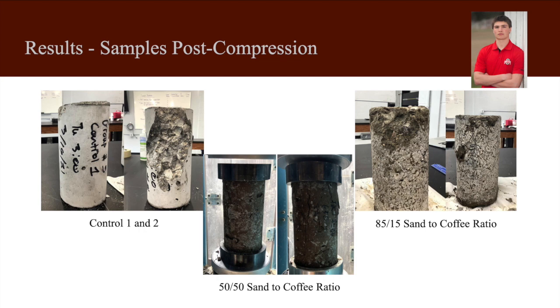Here are the cylinders post-compression tests. The biggest thing that was observed was how the control sample failed compared to how the samples with the coffee grounds failed. The control sample looked as if it broke off in chunks, as you can see on the left side, and the time span of the failing was almost an instant. For the coffee grounds, the failure was more of a crumbling, and the crumbling took place over the duration of the test. In summary of the results, the coffee grounds negatively affected every single statistic that was measured for the purpose of our experiment.